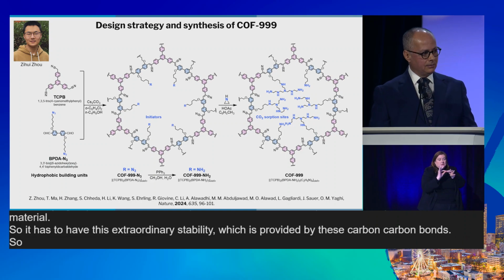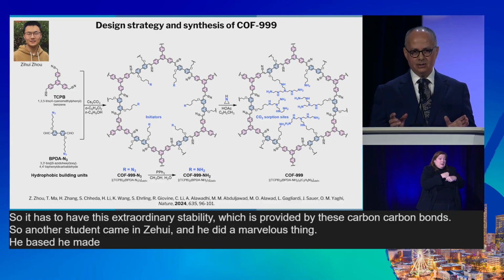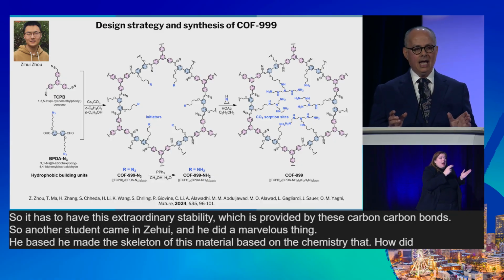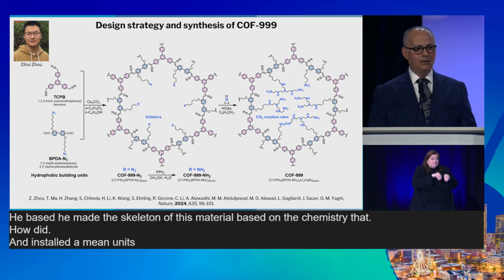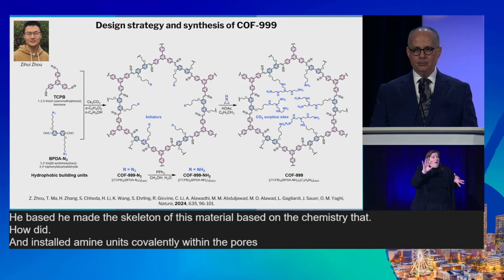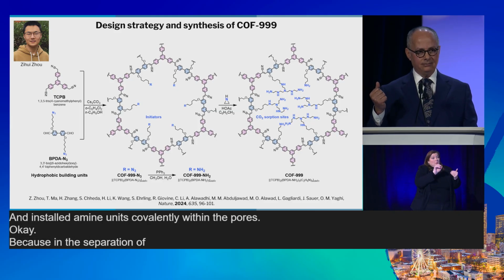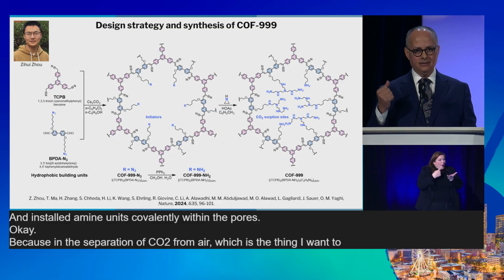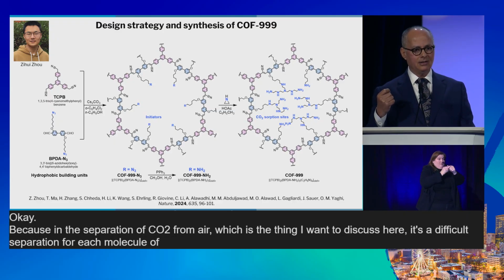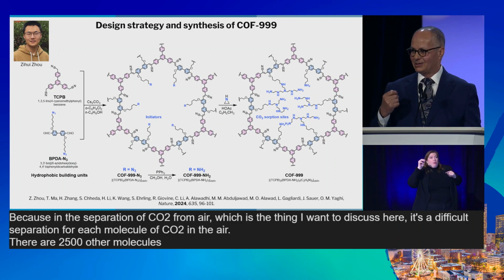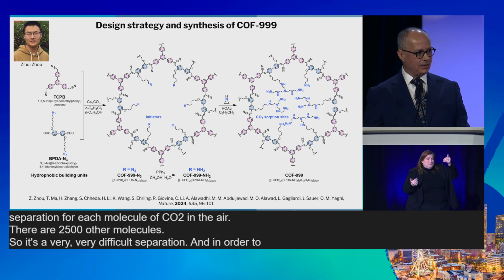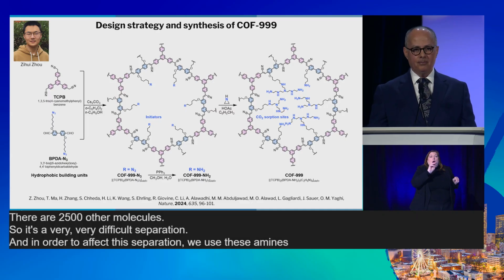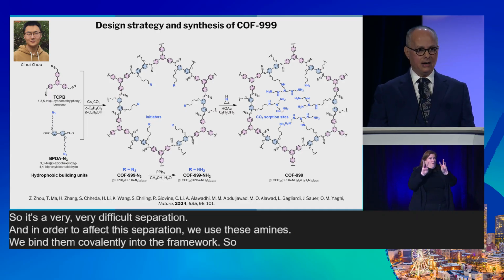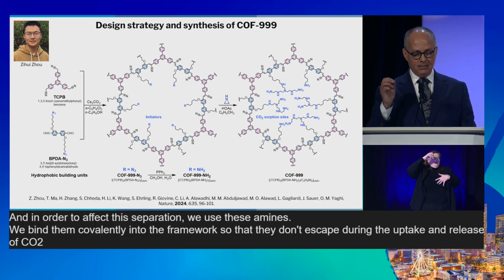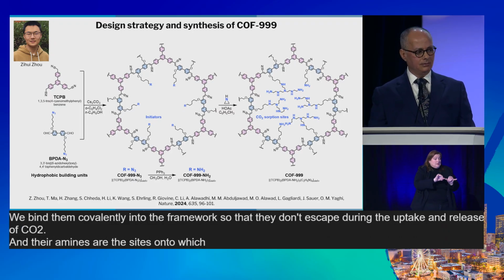So another student came in, Zihui, and he did a marvelous thing. He made the skeleton of this material based on the chemistry that Hao did, and installed amine units covalently within the pores. Because in the separation of CO2 from air, which is the thing I want to discuss here, it's a difficult separation. For each molecule of CO2 in the air, there are 2,500 other molecules. So it's a very, very difficult separation. And in order to effect this separation, we use these amines. We bind them covalently into the framework so that they don't escape during the uptake and release of CO2. And the amines are the sites onto which CO2 will bind.